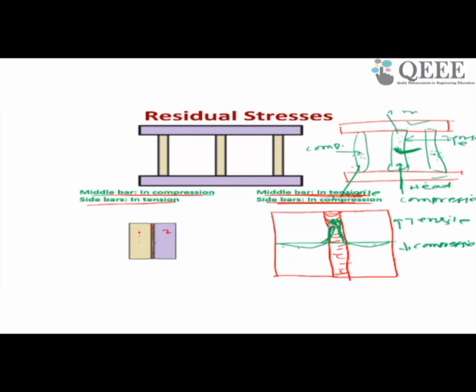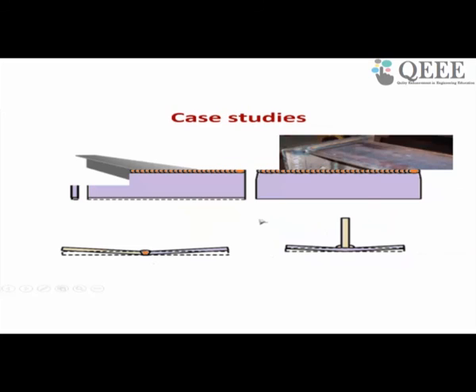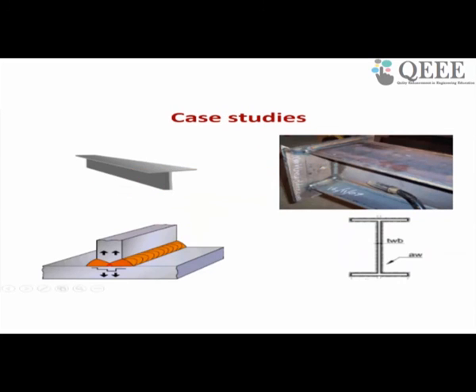This residual stress will be maximum up to the yield stress of the material. If the yield stress of a material is high, then the residual stress will also be high in that particular case. So in the weld zone, you get tensile residual stress, and away from the weld zone, in the base material, you get compressive residual stress. Similarly, in casting you also get different processes. So you can do a case study. You take all the pieces, these are the different joints, and try to develop the kind of residual stress in this process.